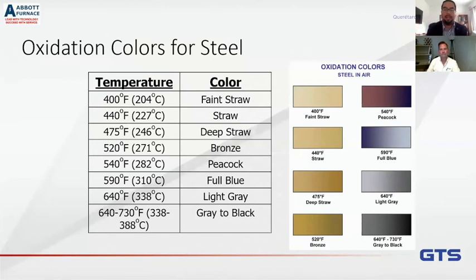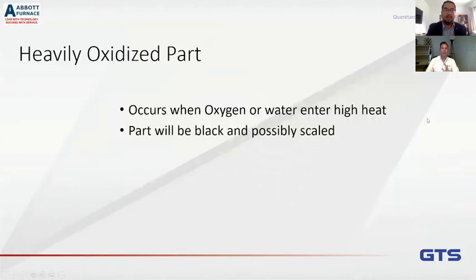I have seen parts really, really bad oxidized. If they are really heavily oxidized, if they're black or gray, or maybe even you'll see them peeling, you'll see the oxide flaking off. That means that it happened in the high heat. Because if you recall from the color chart, you notice how it keeps getting darker. Once you go very high in temperature, that oxide becomes very dark gray to black. And that indicates that you have a leak in the high heat area.